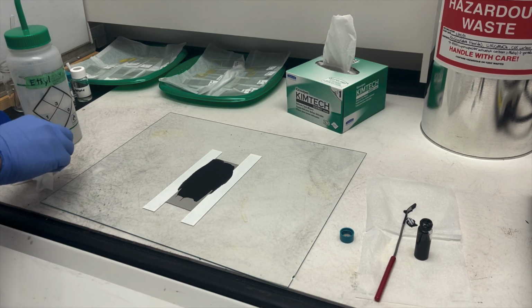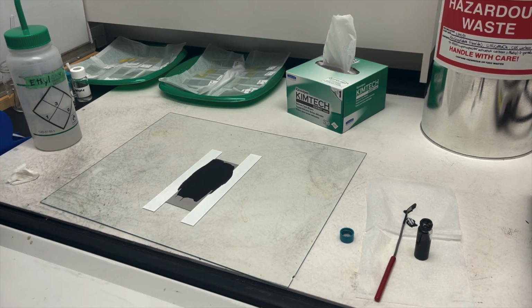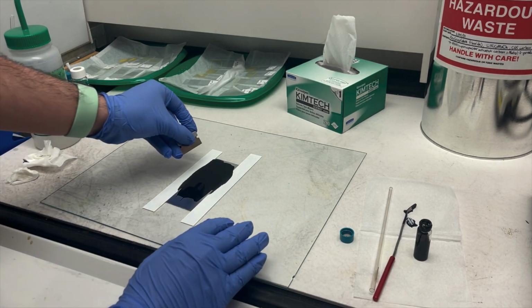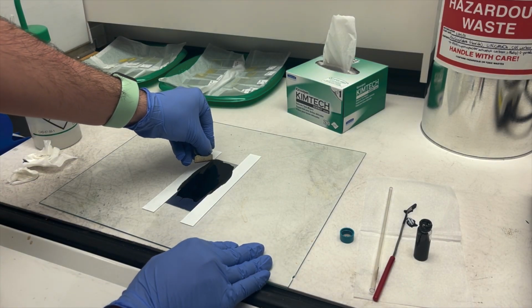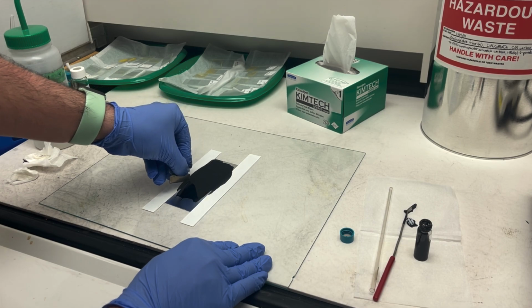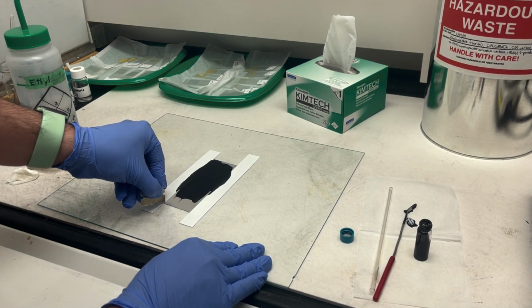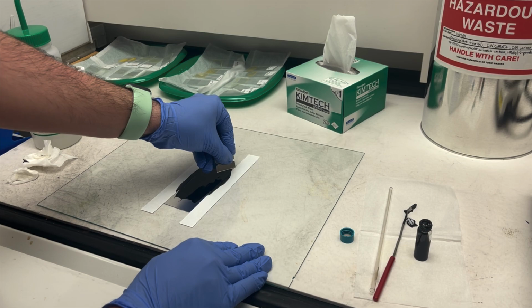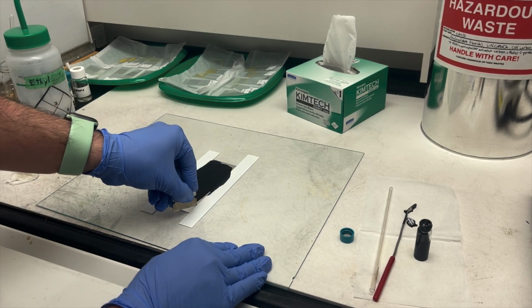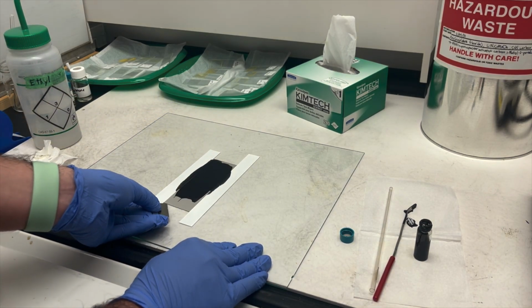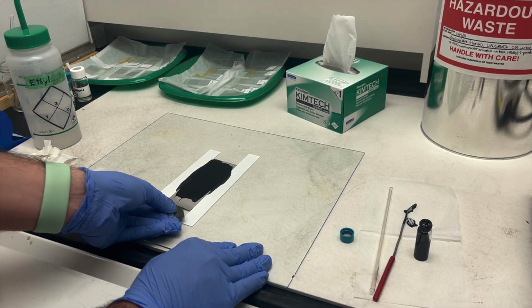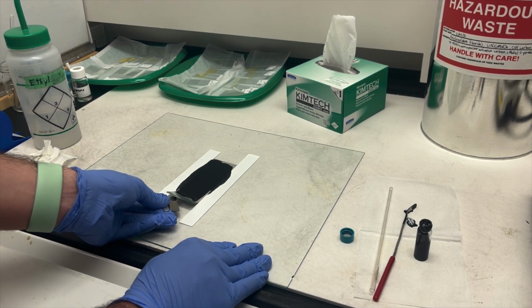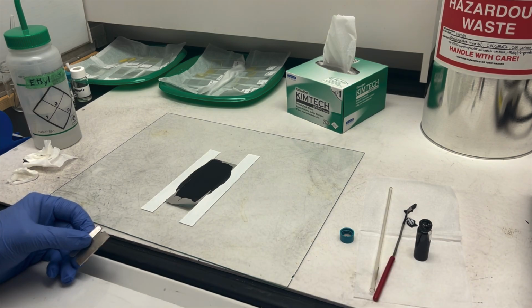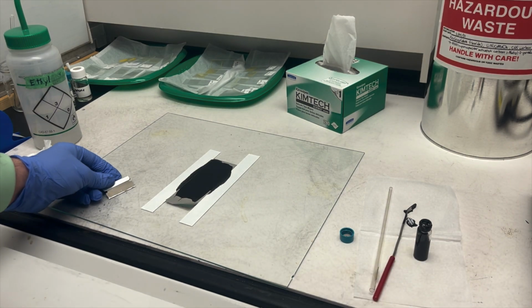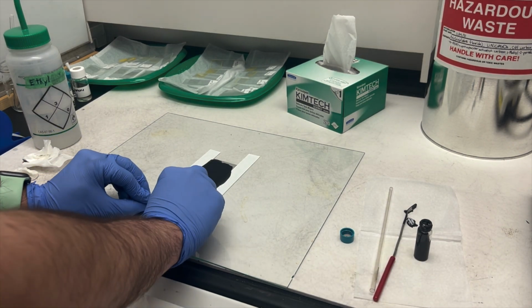The glass rod will then be cleaned with another ethanol-soaked Kim wipe. We now need to transfer the casted foil from the glass sheet to the hot plate. We will do this by using the edge of a razor blade to cut along the tape on both sides and remove the sheet gently. Ideally, the sheet should be kept as flat as possible so the slurry doesn't pool in other areas and remains evenly distributed throughout the piece of foil.